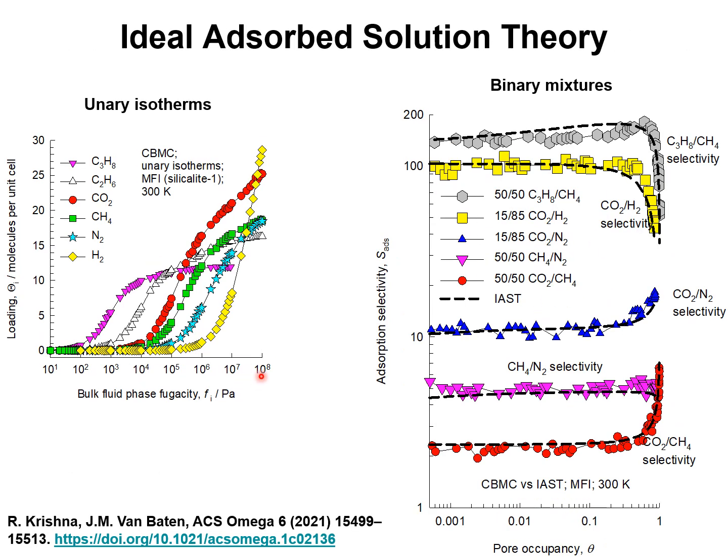The mixed gas Langmuir model is unable to provide a quantitative description of mixture adsorption in scenarios in which the gas constituents have large differences in saturation capacities. In general, it is necessary to use more rigorous models for mixture adsorption equilibrium, such as the ideal adsorbed solution theory of Myers and Prausnitz.